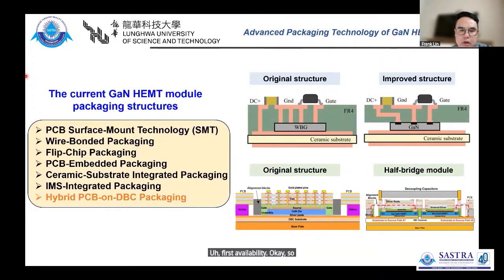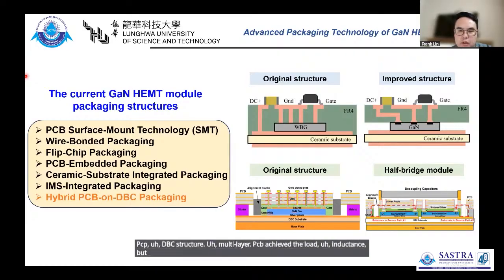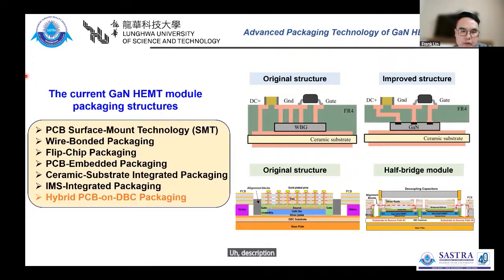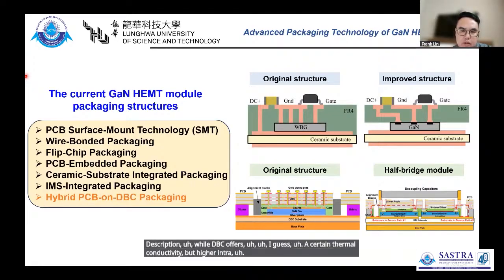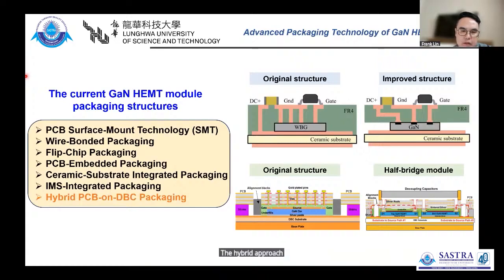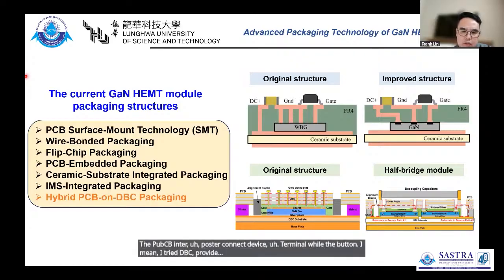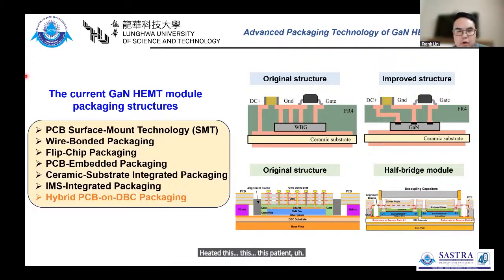Okay, so finally, let's talk about the hybrid PCB on DBC structure. Multi-layer PCB achieves low inductance but poor heat dissipation, while DBC offers excellent thermal conductivity but higher inductance. The hybrid approach combines the best of both. In this design, the top PCB interposer connects the device terminals, while the bottom aluminum nitride DBC provides heat dissipation. This reduces parasitic inductance to about 1.2 nanohenry and 3.5 nanohenry.